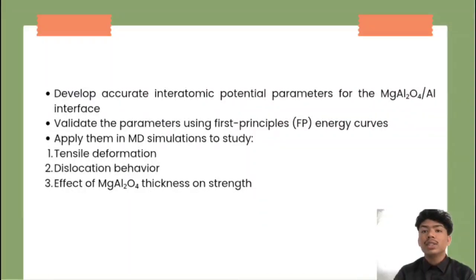Once the potentials are fitted, the next objective is to validate their accuracy by comparing them to the first principle results. This step ensures the fitted models accurately represent the real atomic interactions. Finally, the validated potentials are applied in MD simulations to study the mechanical behavior of the interface. The simulation aims to uncover how the interface responds under tensile loading, how dislocations form and evolve, and how the thickness of the magnesium aluminate ceramic layer affects the composite's mechanical performance. These objectives collectively support the broader goals of revealing the atomic scale strengthening mechanism and improving the design of high-performance aluminium composites.